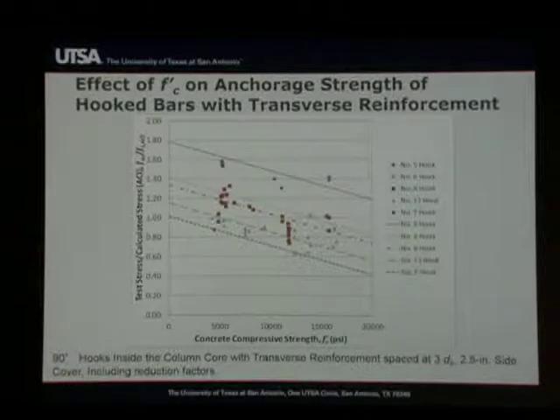This one shows, again, the effect of f'c. The previous set was bigger. It didn't have any transverse reinforcement in it. In this case, I'm showing you results for joints that actually have transverse reinforcement, and there are certain requirements within the code, and the spacing of 3 bar diameters in the hooks is kind of a dividing line. And so all of these comply with 3 db spacing in the transverse reinforcement, so they all meet the requirements in the code, and we see that the behavior is no different.